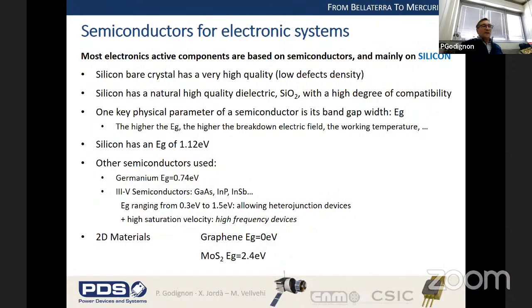So focusing on semiconductors, as you may know, most of the semiconductor devices you can use in all the electronic systems around you are based on silicon. Silicon has several advantages. It is cheap, which is one big advantage for the industry, but it's also a material which is quite common, and you can get very high quality material with very low defect density, which is important to build electronic devices. Another very good advantage is that it has a natural high quality dielectric, which is almost compulsory to build any kind of electronic structure.